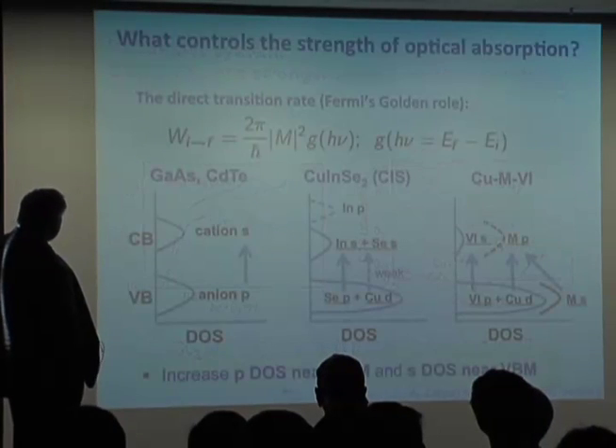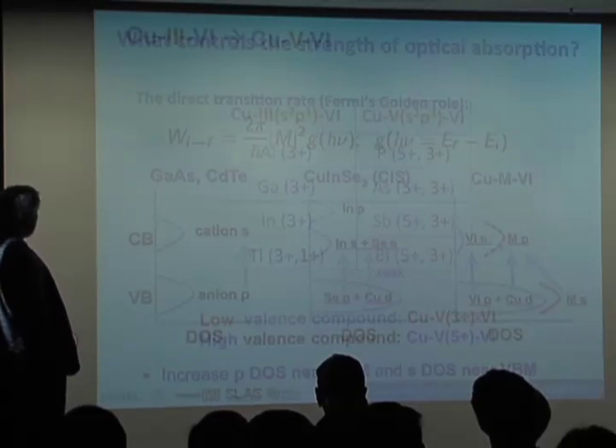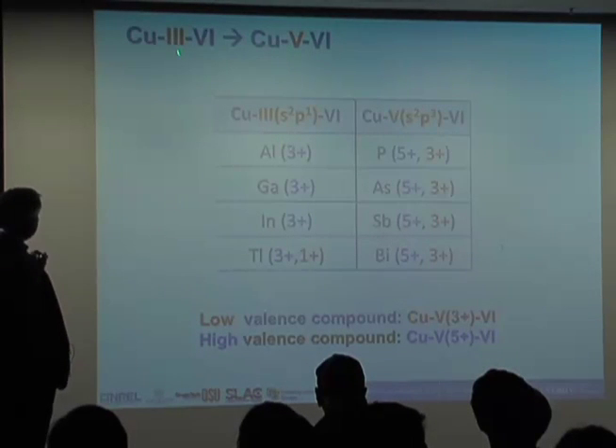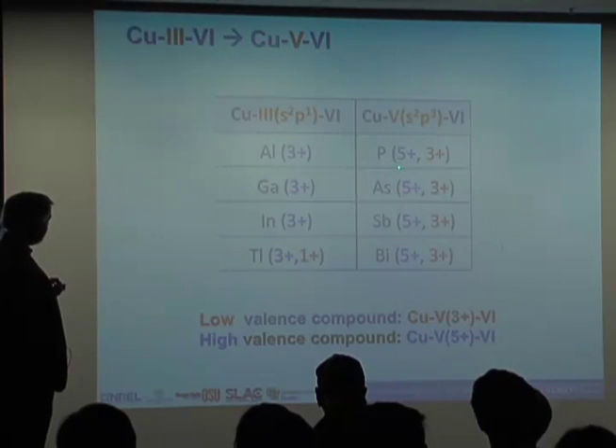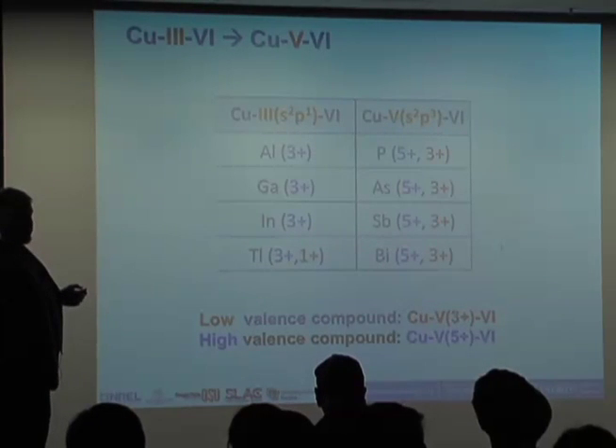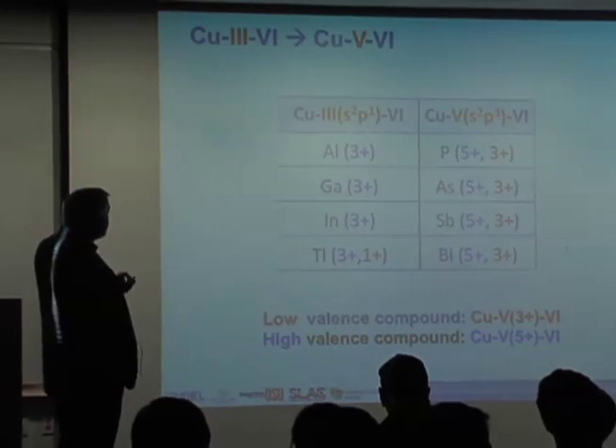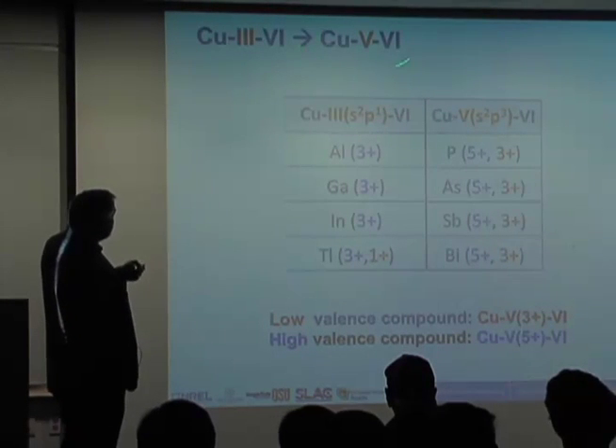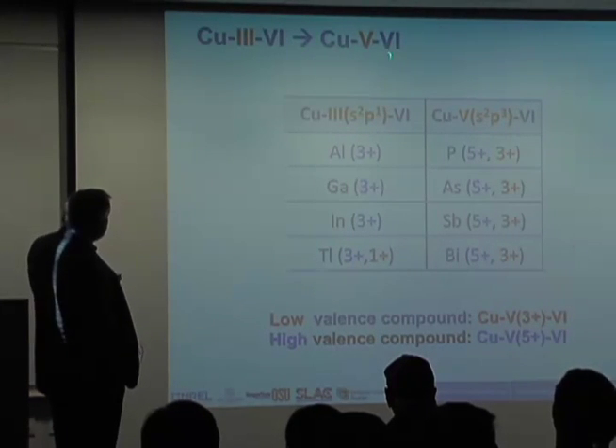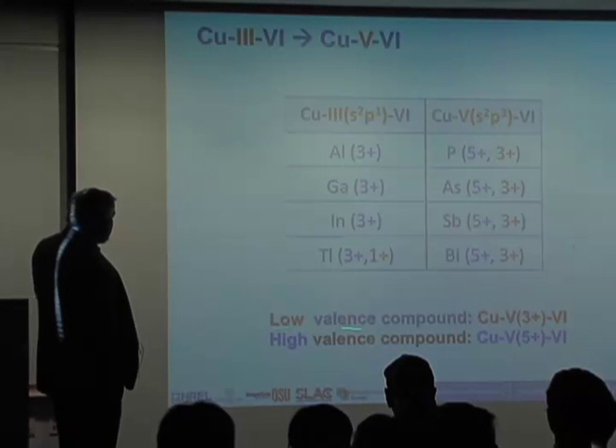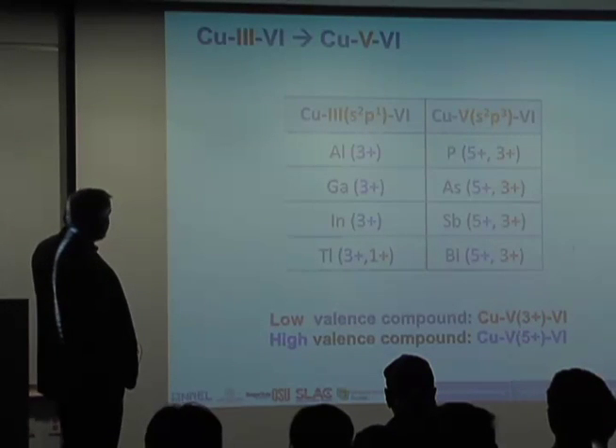And so to do that, we actually went to another system, which was to say, let's look at the copper 5-6 system, where now the 5 element can actually be both in the 5+ or the 3+ oxidation state. Whereas in a 3 system, only thallium could be aliovalent. All of these systems can exist in the 3+ and the 5+. So we can very quickly look at the absorption spectra theoretically, and eventually, as I'll show you experimentally, for these copper 5 systems. Compare the low valence system with the high valence system.